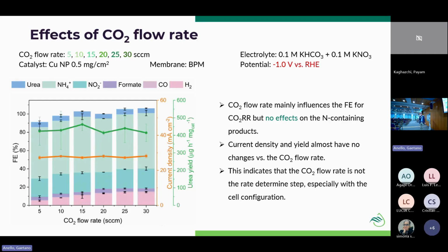This is quite difficult because CO2 electrolysis has a higher overpotential than nitrate. Nitrate reduction is more favorable than CO2 reduction. So from the engineering perspective, we can think about systems where we would have a slightly lower nitrate concentration near our electrode and can actually boost the CO2 concentration near the electrode surface. Maybe this could be a means to push the balance a bit more towards CO2.